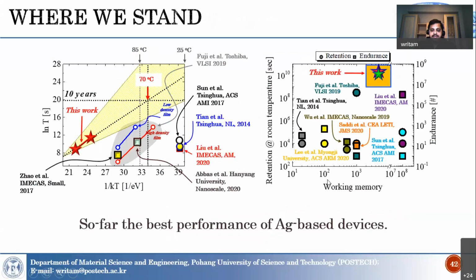Now, if we compare this with other reported work, it shows that the silver devices with this kind of scheme can continue for 70 degrees centigrade at 10 years. Why I chose silver: it is very difficult to get excellent retention because silver's diffusivity is normally high, so whenever your channel is there, it can break easily. That is the reason we chose this topic, to increase the endurance behavior of the silver-based devices. Previously, a similar kind of design with silicon dioxide was proposed by Toshiba in 2019.